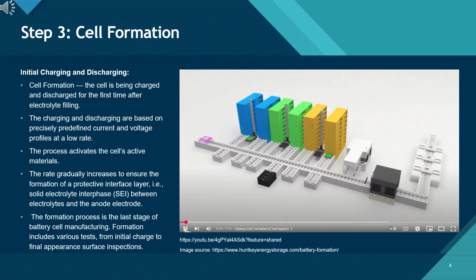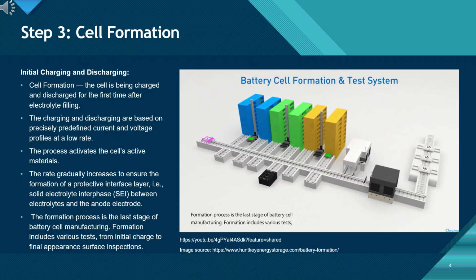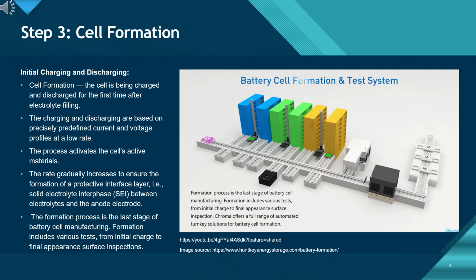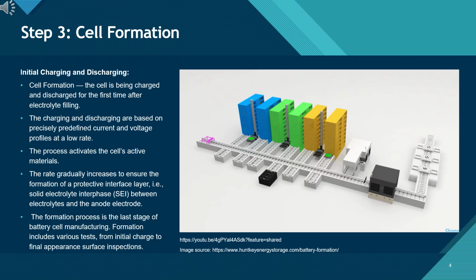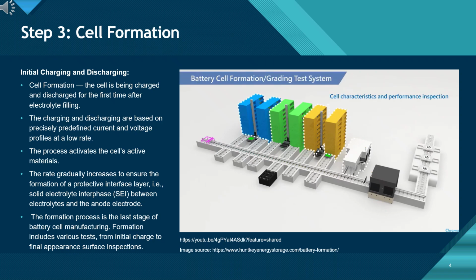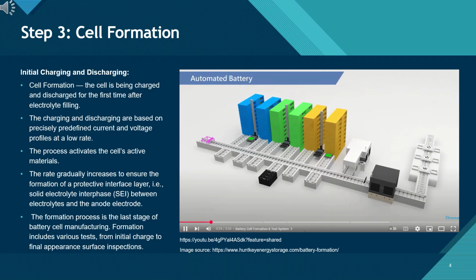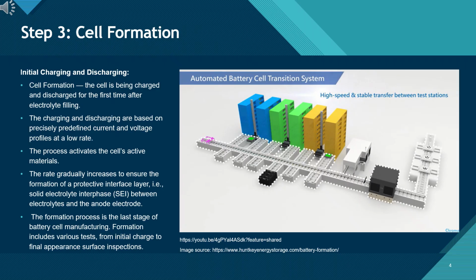At this stage, the cell is charged and discharged for the very first time after the electrolyte has been filled. This is not done at full speed or high current. Instead, it follows very carefully controlled current and voltage profiles at a low rate. The purpose here is to activate the cell's active materials, and to gradually build a protective interface layer between the electrolyte and the anode. This layer is known as the solid electrolyte interface, or SEI.